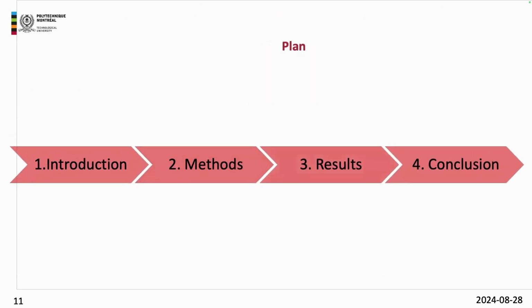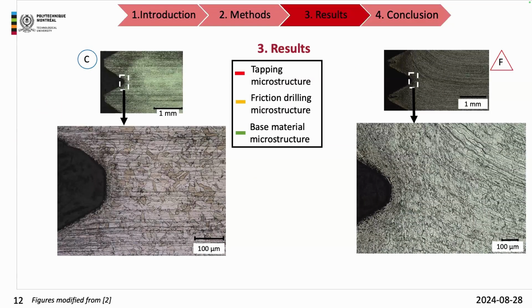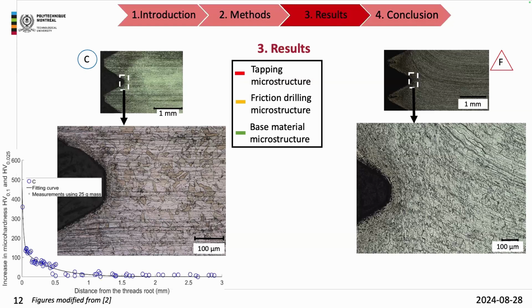Let's now present and discuss the results. First of all, we start with the micrographic observation. Here, the first thing that we can notice is that on your left is the conventional specimen, and on your right is the flow form specimens. For the conventional specimen, there are only few effects here for the first millimeters, and then we found equiaxed grain that is typical from this metal since it's from hot rolled bars. And for the flow form specimen, we know that the grains are deformed and also refined.